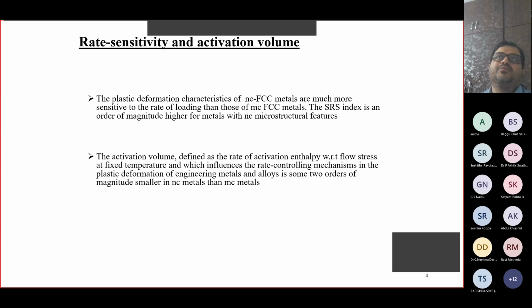These strength and ductility are mutually exclusive properties conventionally. For example, if you make a very strong material, it's not ductile enough to make it into sheets, plates, and so on. Whereas if you make a very ductile material, you cannot make it strong. One you get at the expense of the other. But getting a really stronger material coupled with really high levels of ductility is still a challenge for engineers to overcome. And while doing so, we evaluate two critical parameters called strain rate sensitivity and the activation volume. Strain rate sensitivity is the change in the flow stress of a given material at a given temperature with the variation of strain rate.